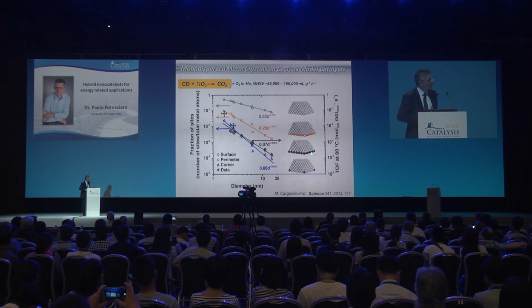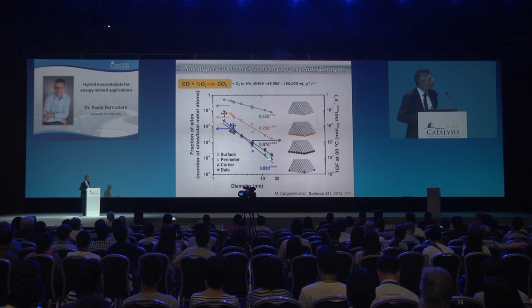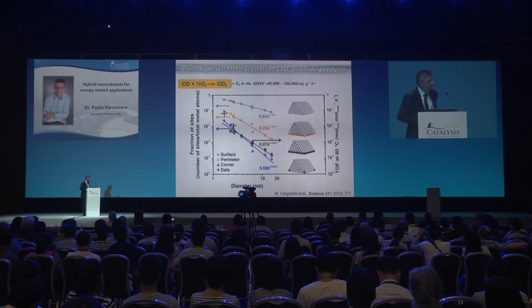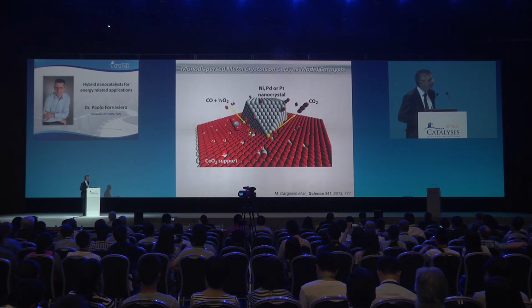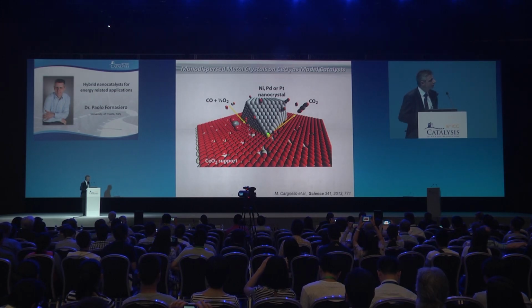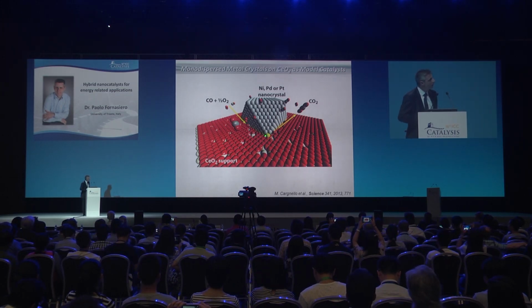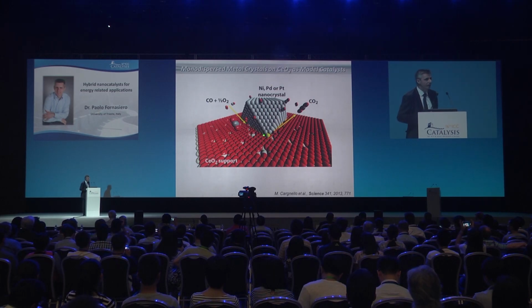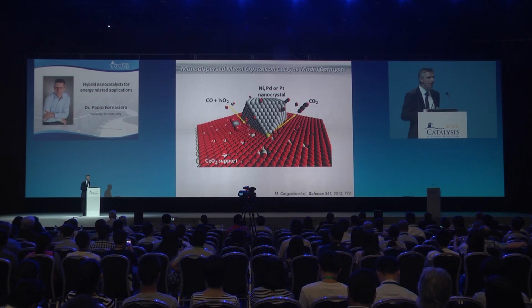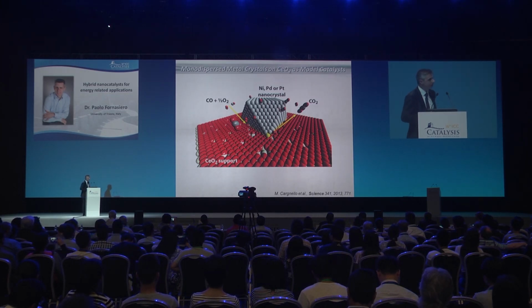And then we plot the turnover frequency, the catalytic activity, against the diameter, and the trend fits pretty well between the two lines, indicating that the reactivity in CO oxidation, for this type of material, really occurs at the interface, and probably the most active sites are those at the corner. So we have to maximize the interface, we have to optimize the number of these sites to enhance the performance of this catalyst.